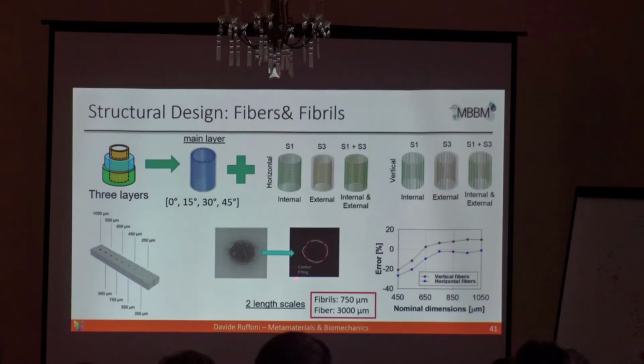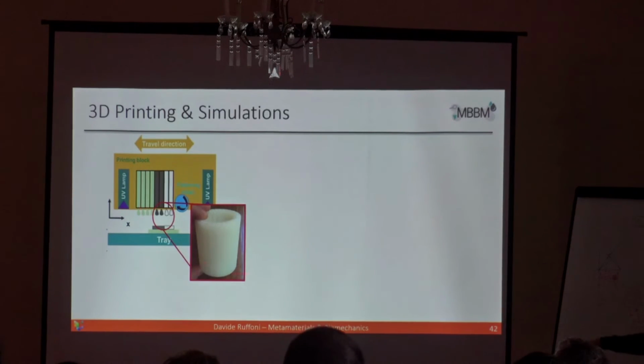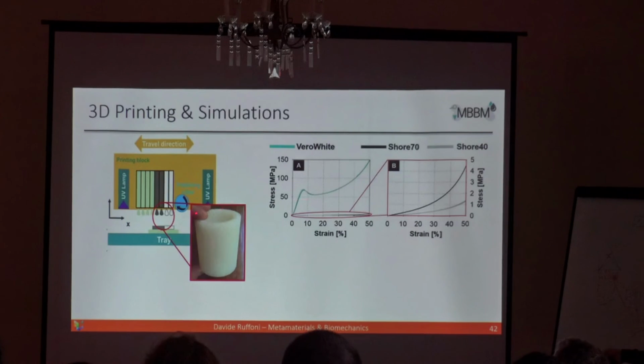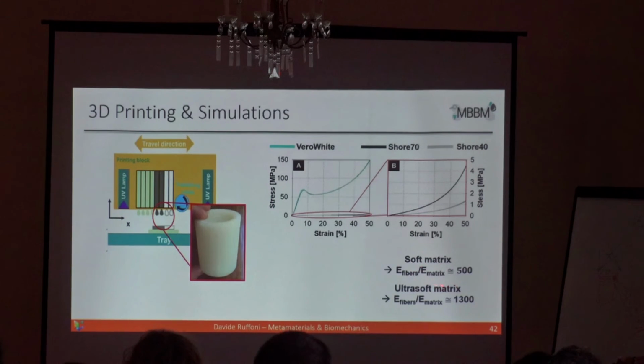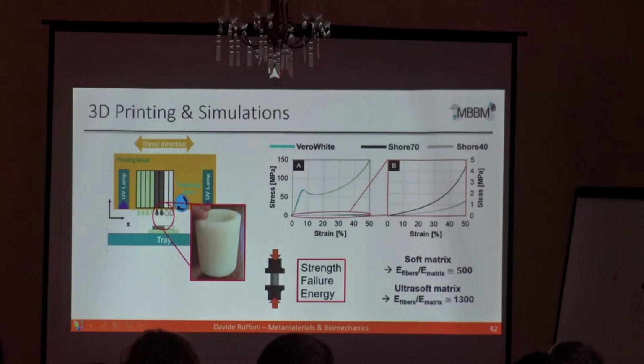So we printed actually 2 types of length scale. We print small fibrils and bigger fibers. Fibers are in the main layer and fibrils are in the reinforcing layer that we call here. Then we 3D printed those structures that look a little bit like this. And we used a stiff polymer for the fibers and a soft polymer for the matrix. Actually, we used 2 types of matrix. A soft matrix where the elastic contrast between fibers and matrix was 500, and an ultra soft matrix where the elastic contrast was more than 1000. And we investigated the mechanical behavior of this with a compression test.